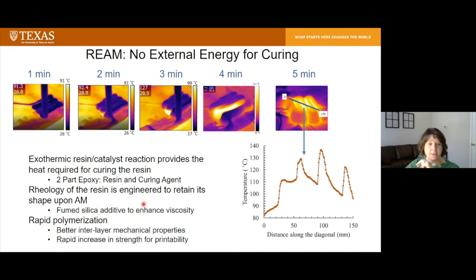The rheology of the resin has to be engineered to retain its shape. So if we used a standard epoxy resin, as mixed, it would not hold its shape. Instead, it would spread out over the build platform. So we used additives like fumed silica to enhance its viscosity. And one of the other things, again, I'll mention is rapid polymerization. That rapid polymerization provides better interlayer or cross-layer mechanical properties because we get some cross-linking across layers. And we get a rapid increase in strength for printability. So once a layer is deposited, as it polymerizes quickly, its strength increases, and so it can support subsequent layers.